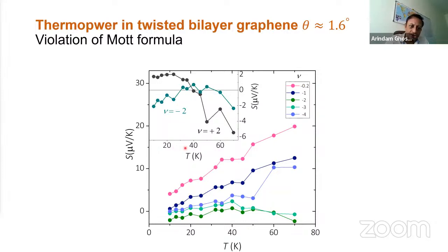So you can see as a function of temperature, the thermopower is tending to a finite value rather than going to zero, which happens, by the way, at other filling factors. Say when the filling factor is 4 or 3, you can see they essentially extrapolate to zero when the temperature goes to zero.